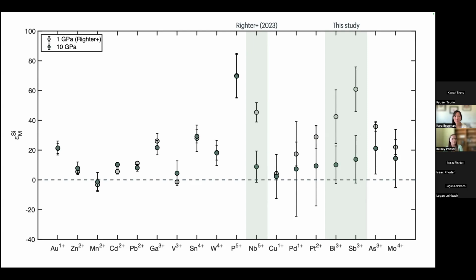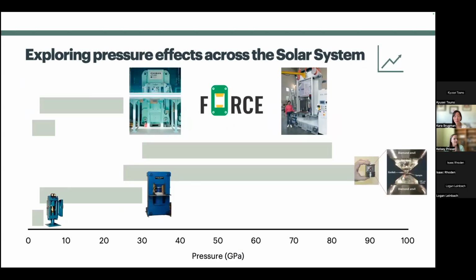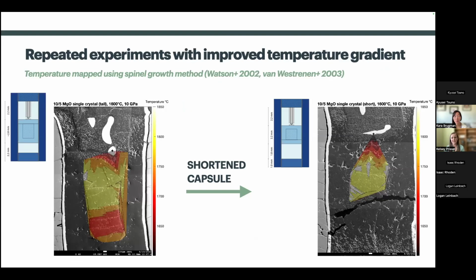Moving forward, I mentioned that we have another round of experiments that we're analyzing. What I did was redo all the experiments in a smaller capsule. So we have these shorter capsules that have a smaller temperature gradient, and my hope is that the error bars, when I'm considering all of this uncertainty, will be smaller. We're waiting for that new data, and then I will calculate it and hopefully refine that plot. It could be that there will be other elements that then have a resolvable effect of pressure. But we're pretty confident about the bismuth and antimony ones, because even despite all that uncertainty, they're still resolvably different.